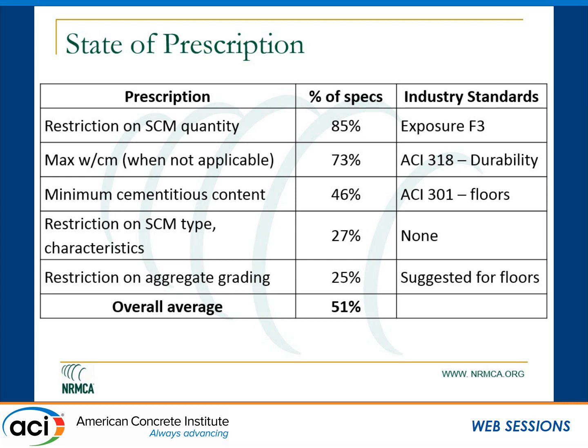The second type of problem is where you have a water cement ratio and the strength that is specified is totally not in sync with the water cement ratio. And so that's another problem where you have, let's say, a 0.4 water cement ratio and a 3,000 psi concrete mixture requirement. And that's sort of a disconnect that causes a little bit of issues over there because they're two different mixes. Okay, 0.4 water cement ratio mix is totally different from a 3,000 psi mix.